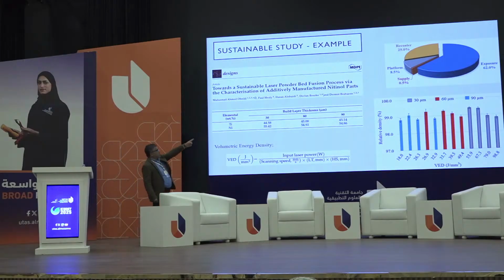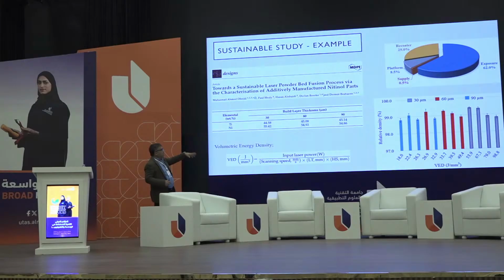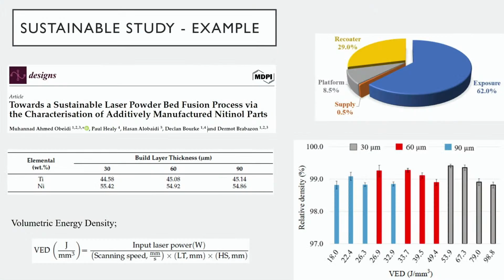So here I calculated the time, and I find the correlation between the time and the build layer thickness. So in future, I only use this correlation to estimate the printing time. I used three different layer thicknesses: 30, 60, and 90 microns.